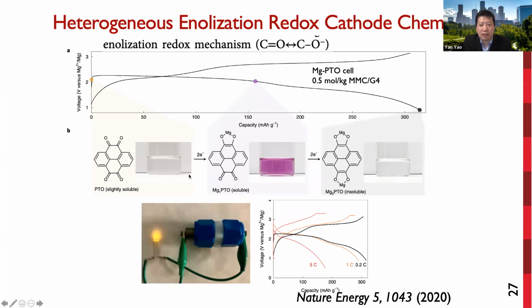So we probed the cathode reaction mechanism using UV visible spectroscopy. The reduction of PTO in the magnesium electrolyte actually is a heterogeneous liquid-solid reaction. We use a Swagelok cell and we discharge to different DOD and then dilute the reaction electrolyte with DME. What we see is that the PTO is reduced to a soluble magnesium 1 PTO intermediate and then to insoluble Mg2 PTO. So the precipitation of Mg2 PTO is a spontaneous process that overcomes the solvent stripping from magnesium.